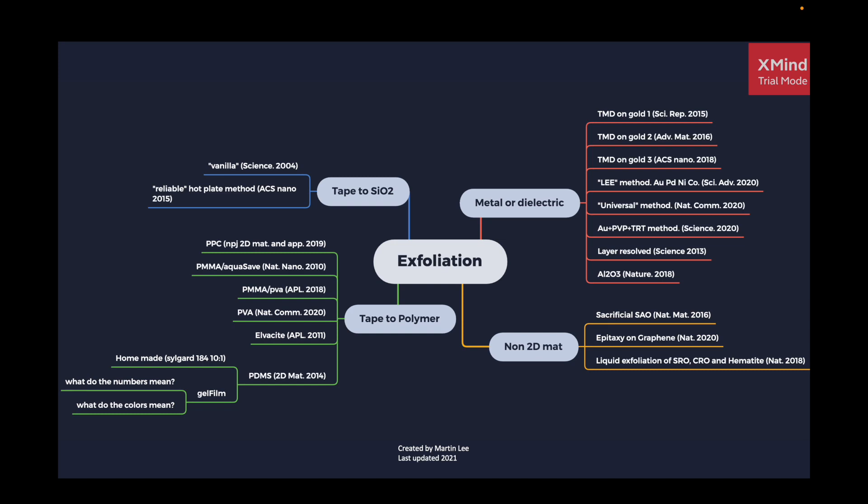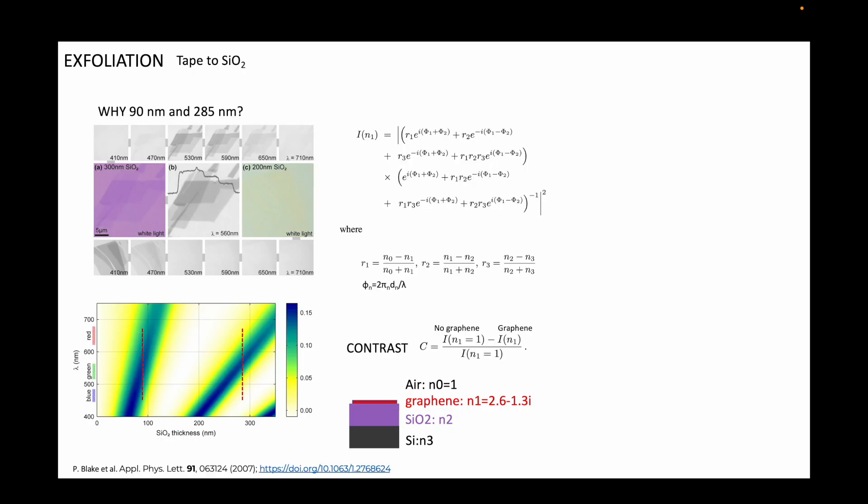We use high-quality silicon silicon dioxide of a certain thickness for several reasons. 1. Silicon wafers can be atomically flat. 2. Graphene silicon dioxide adhesion energy is surprisingly high, as reported by the group of Scott Bunch. 3. The thickness of 90 nm and 285 nm give large improvements in the optical contrast.